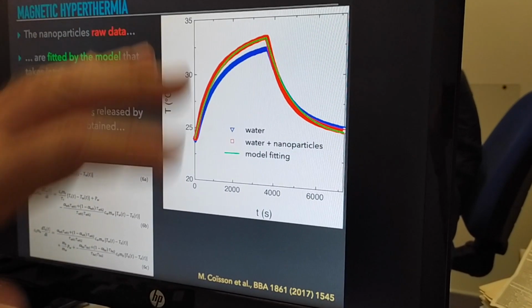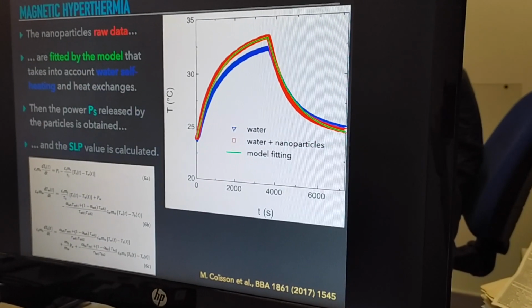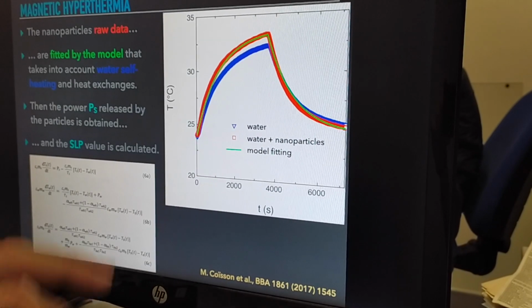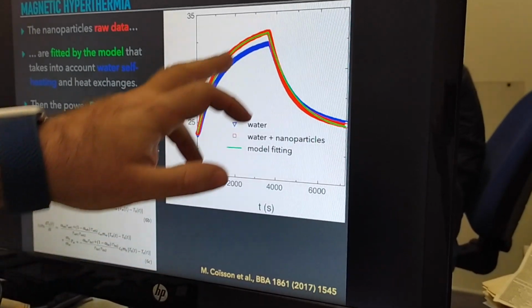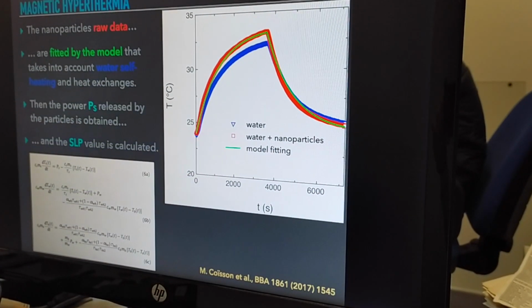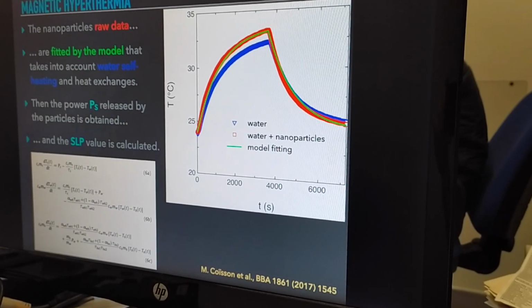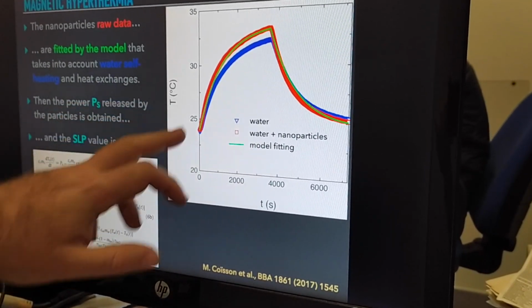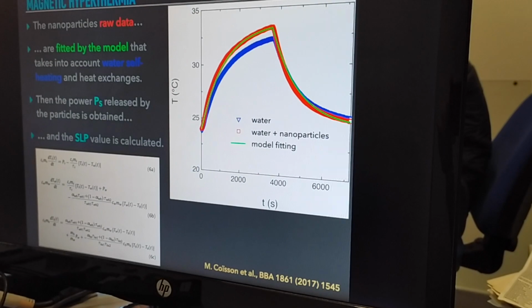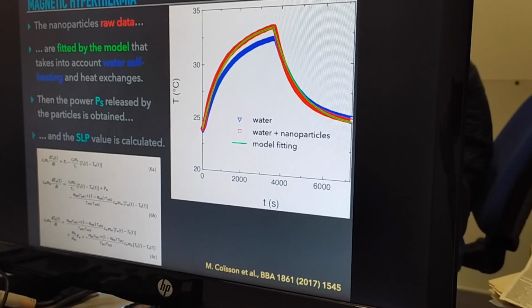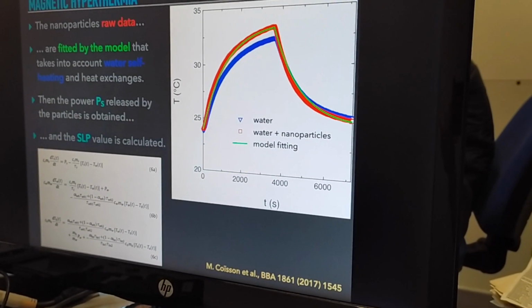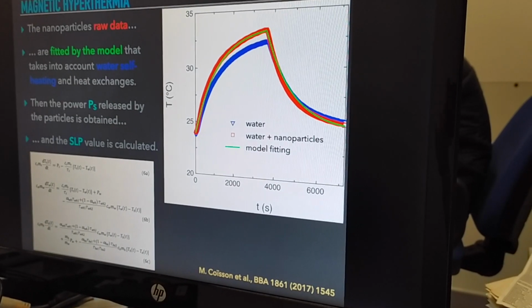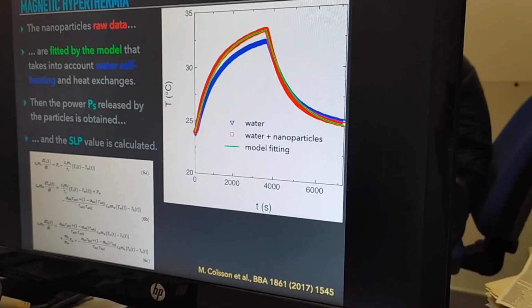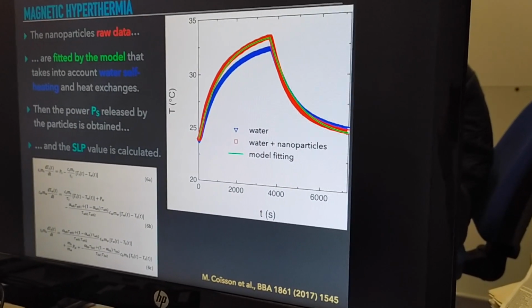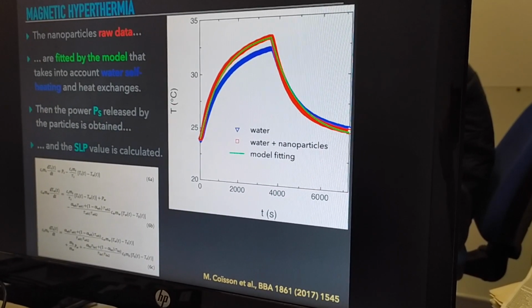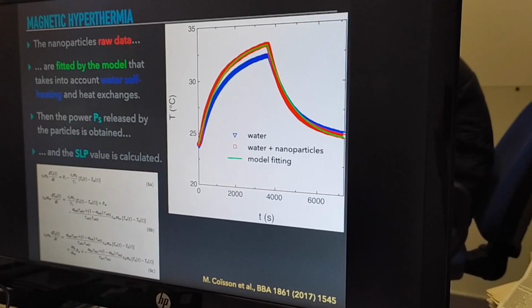By fitting the experimental data and through a suitable calibration of the setup that involves an accurate modeling of the blue curve here, just the water, it is possible in the end to fit the data with the green curve here and extract a parameter that is called the specific loss power that gives you the heating capability of the particles. The specific loss power is the power, the watts, released by the particles per unit mass.